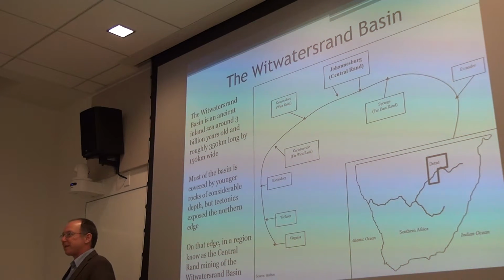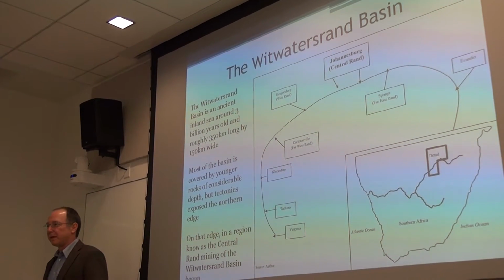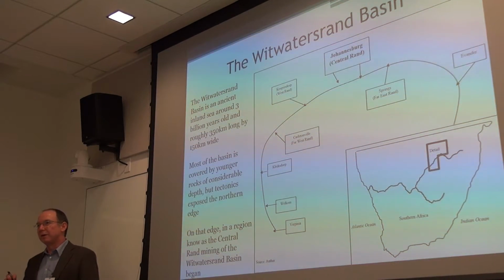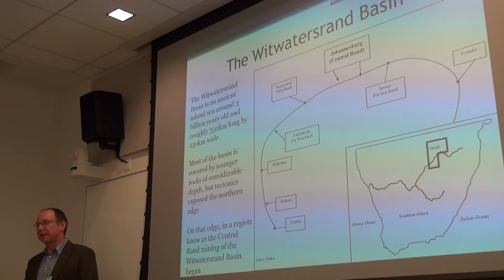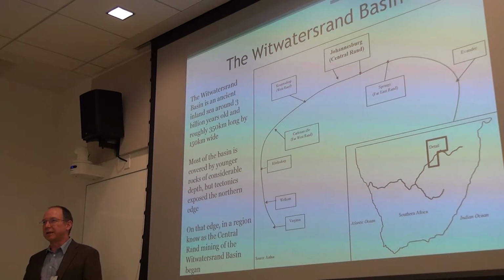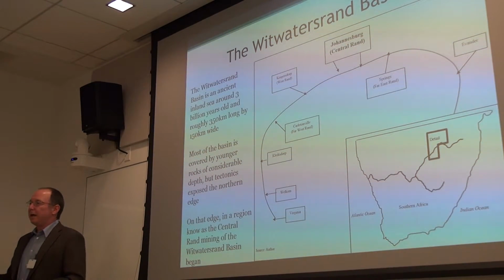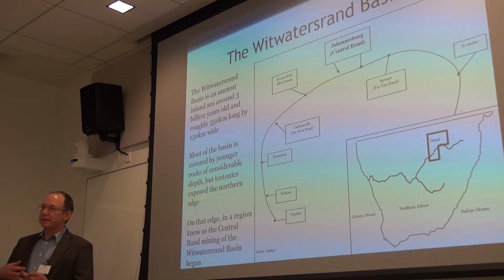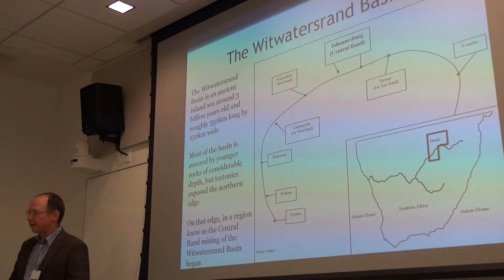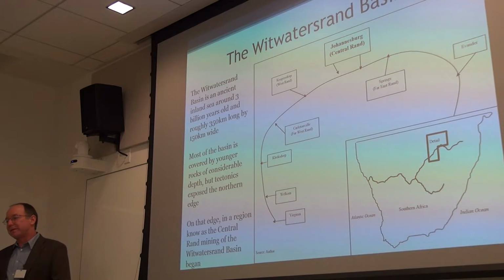Problem was, as you go deeper, you get to gold deposits which aren't oxidized. It's called the sulfide zone. And the gold doesn't get extracted with the traditional technology, which is just crushing it and putting it across lead, and then the gold sinks through the amalgam plates, and then they would get their gold that way. When you get into the sulfide zone, the gold gets chemically wrapped up, and it doesn't just sink through the lead plates. And because of that, it's necessary to find another way.